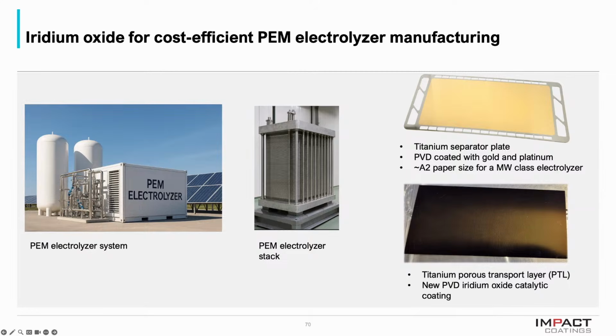To the right-hand side here, you have 2 components. On the top, you have a separator plate made of titanium. This is usually plated or coated with gold and platinum. It's about the size of an A2 paper for a megawatt class electrolyzer. And on the bottom, you have a titanium porous transport layer. It's kind of like a titanium sponge that is flat, you could say. These we routinely coat. The main purpose is to provide electrical conductivity that should be stable throughout the lifetime of the stack. But to add further value here, we move into the PVD iridium oxide, and this coating is catalytic, and it opens up a new field for us.